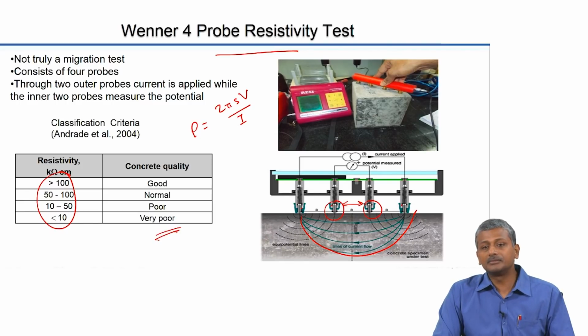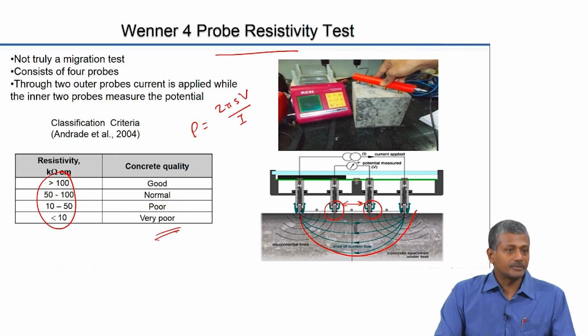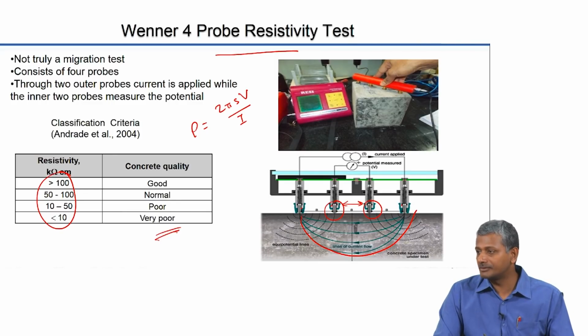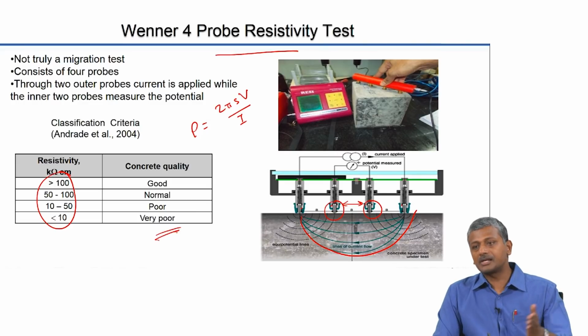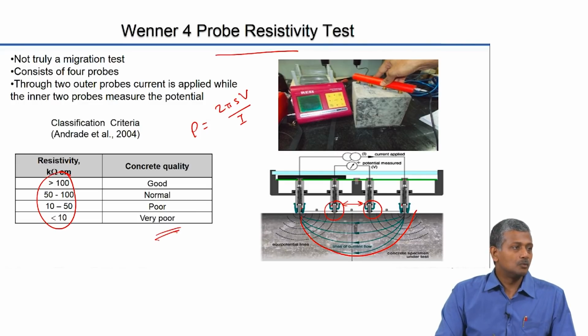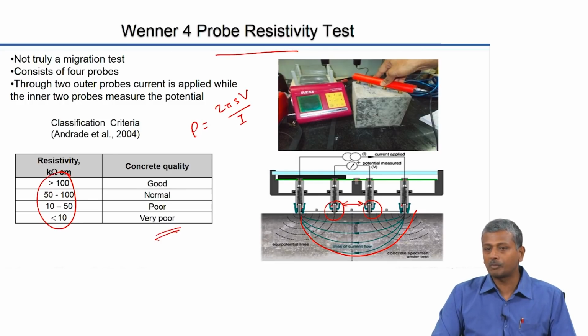So, there is a difference of nearly 6 to 7 orders of magnitude of the resistivity between dry concrete and moist concrete. You can get that level of difference. So, again here, just like your torrent air permeability test, what you need to do is go with the moisture meter first, determine whether your concrete is properly saturated, and then conduct the test to get suitable readings.